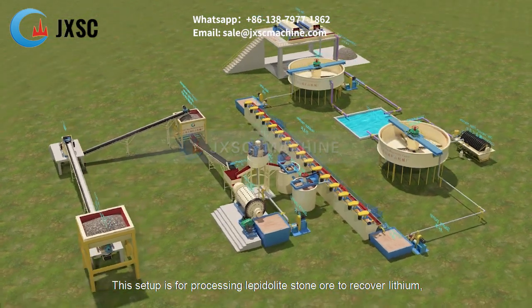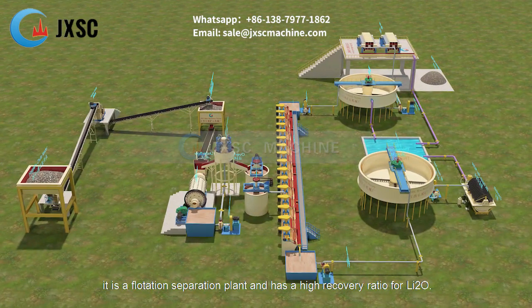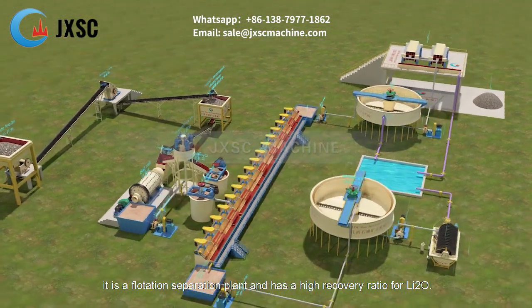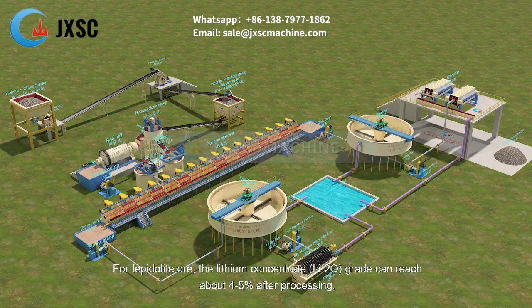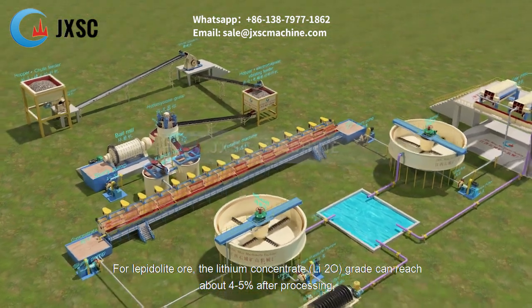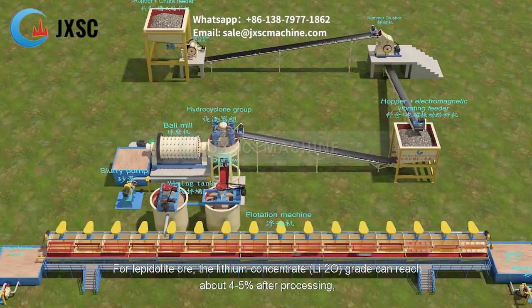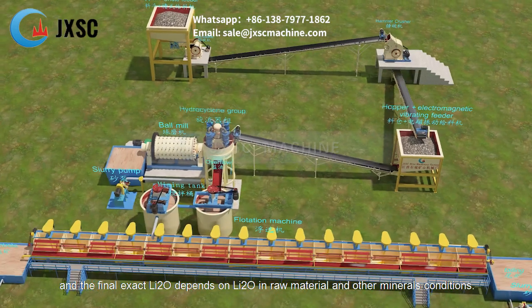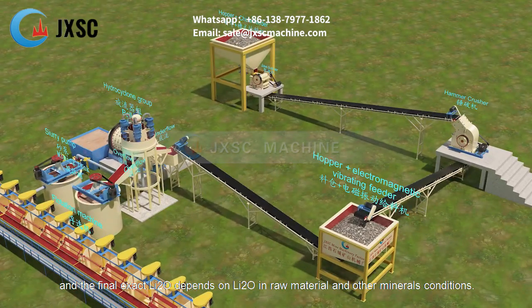This setup is for processing lepidolite stone ore to recover lithium. It is a flotation separation plant and has a high recovery ratio for Li2O. For lepidolite ore, the lithium concentrate Li2O grade can reach about 4 to 5% after processing, and the final exact Li2O depends on Li2O in raw material and other minerals conditions.